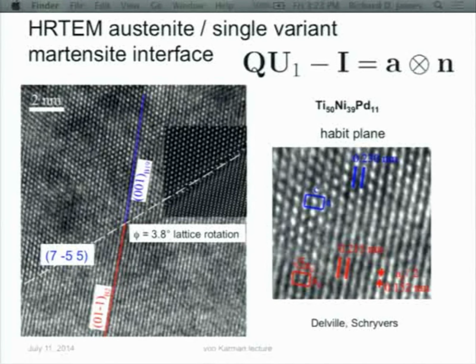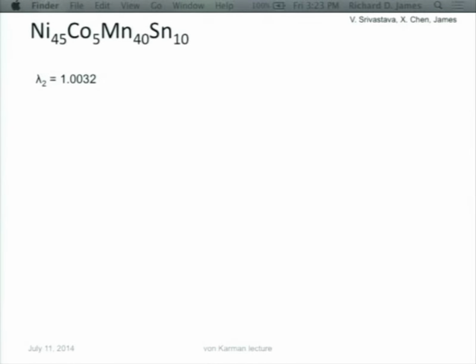There's a picture of one of those interfaces at high resolution, and in fact the normal to the interface was measured. This is the austenite phase down here. This is the martensite phase. And the normal agrees very well with the calculation, and the angle in Q is 3.8 degrees, and so forth. So we see many of those interfaces in alloys which have been tuned to make lambda 2 equals 1. By now this has been done in lots of systems, and it seems to be independent of material. So it's a way to make low hysteresis alloys.